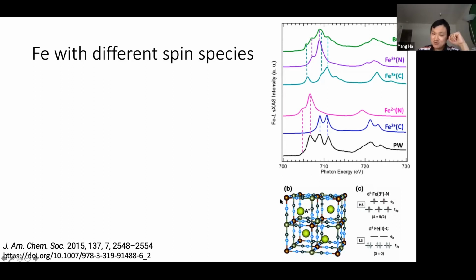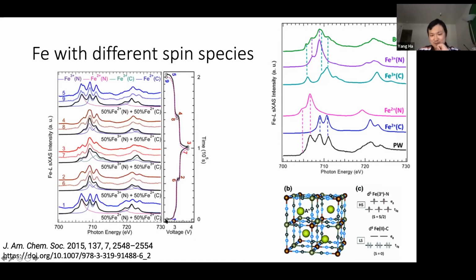So when we charge and discharge the systems, we can have 4 species. We can have the ferrous and the ferric, and we can have the high spin and the low spin. And the interesting part is when we cycle this Prussian blue, when we charge it, we actually have 2 stages that are well separated. So we have the first stage and the second stage when it's fully charged, and then we also have 2 stages that are discharged, and it's very reproducible in the second cycle.